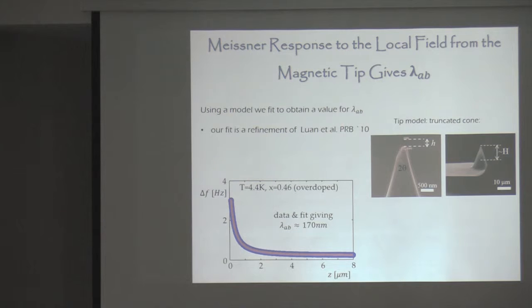The problem is also that the tip, you can see here, this is SEM. I can't see where magnetism is. So there are domains. This is going to affect things too. So there's uncertainty. It boils down to a couple of dozens of nanometers. If you're looking for differences in lambda, there are better techniques. But it's really hard to get the absolute value.